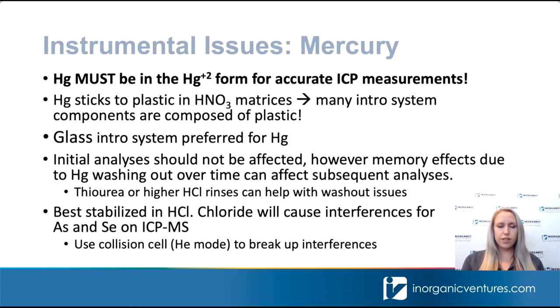The best solution for this is to add a little bit of hydrochloric acid to your matrix. This will stabilize mercury and prevent any adsorption to plastic. As mentioned in the previous slide though, adding this hydrochloric acid will cause that interference on your ICP mass spec for both arsenic as well as selenium. So make sure you are using that helium mode if you are adding hydrochloric acid to your matrices for mass spec.